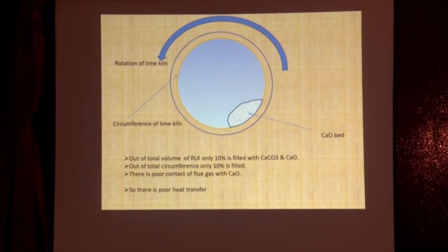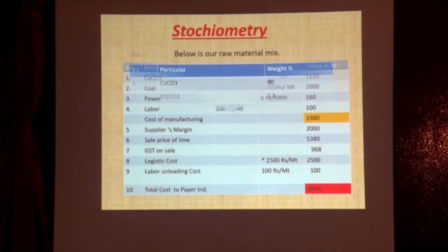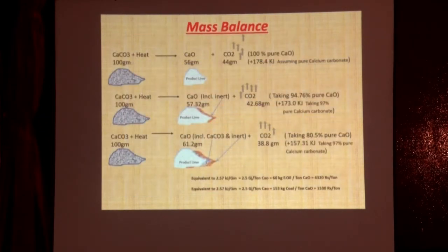Even so, this fuel consumption is still high, because our theoretical energy requirement is only 60 kg at 80% purity, and they are consuming 160 kg. If I take 75% efficiency of the rotary lime kiln, it should not be more than 80 to 90 kg. So there is still a lot of scope.